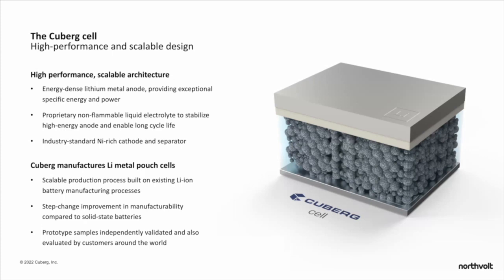And honestly, I do see this type of approach as being the most likely type of cell architecture to get commercialized for air mobility. Essentially, we have replaced the graphite anode in the lithium ion cell with a much, much lighter weight lithium metal anode. Lithium is ultimately the lightest anode material that you can use on the periodic table. It provides exceptional specific energy and power, which is exactly what you need for air mobility.